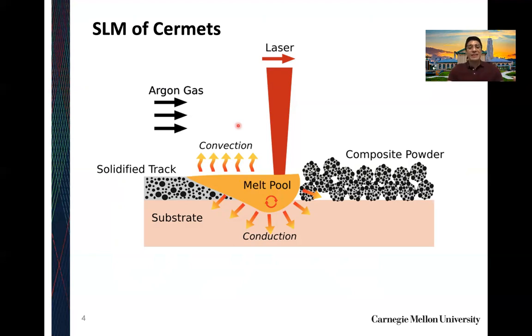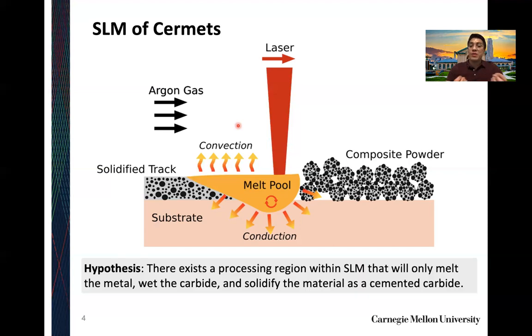So given the fact that this is a very complicated, very volatile process, it's pretty difficult to model this, especially when we are introducing a new novel material system like a composite powder. But with that being said, we would take an experimental approach, and we have a hypothesis where we believe there exists a processing region within selective laser melting that will only melt the metal, thus wetting the carbide that isn't melted, and therefore almost immediately solidifying the material as a cemented carbide.